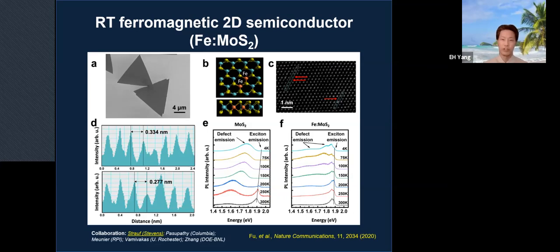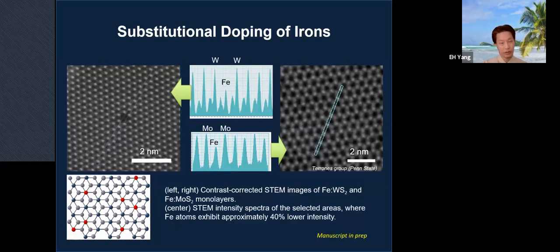So among those characterizations, number one is to confirm the substitutional doping. Substitutional doping means you replace, for example, you have molybdenum atoms, and you have these iron atoms, right? Iron atoms basically replace these molybdenum atoms. So that's substitutional doping. This is different from interstitial doping, where iron atoms are somewhere between the lattice, right? In that case, you don't really realize ferromagnetism reliably. And if you have adhesion or some residues, basically it's useless. So it is important to see that the atoms are substitutionally doped.